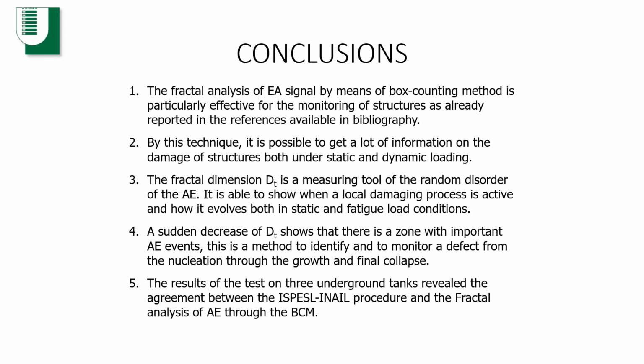It works both in static and fatigue load conditions. A sudden decrease of fractal dimension shows that there is a zone with important acoustic emission events, that is, a method to identify and to monitor a defect from the nucleation through the growth and the final collapse. Both methods used, fractal analysis with box counting and acoustic emission with the ISPESL-INAIL procedure, are in good agreement.